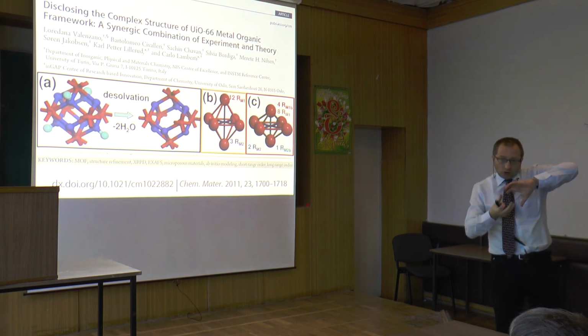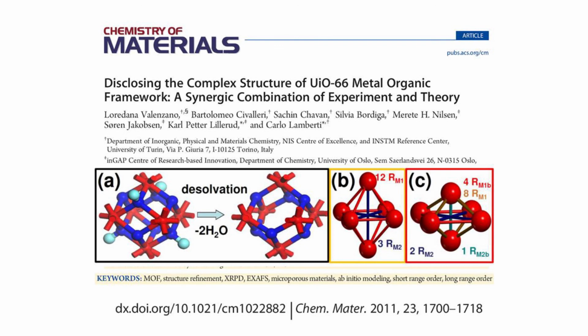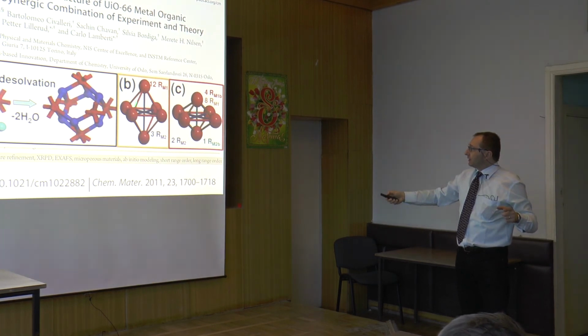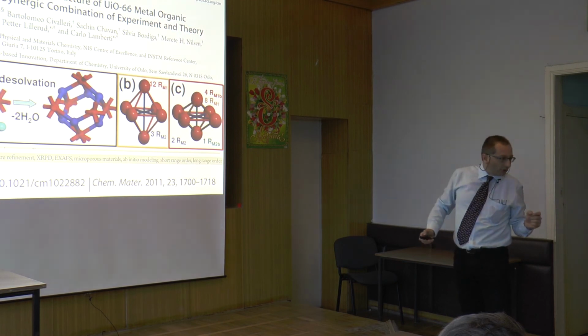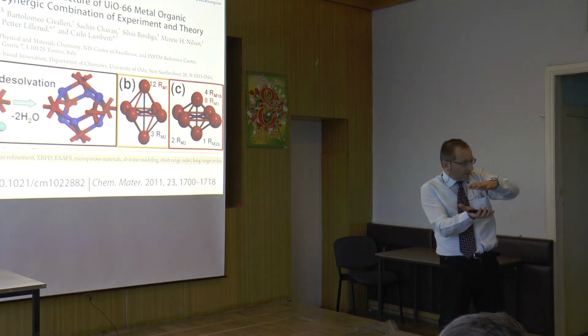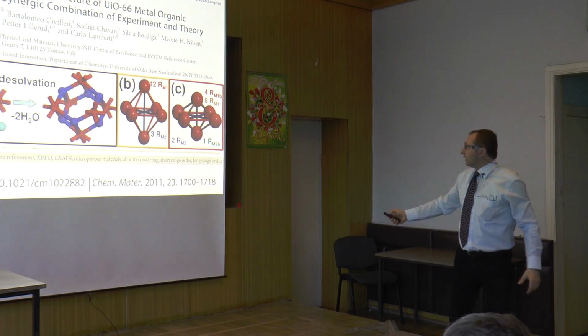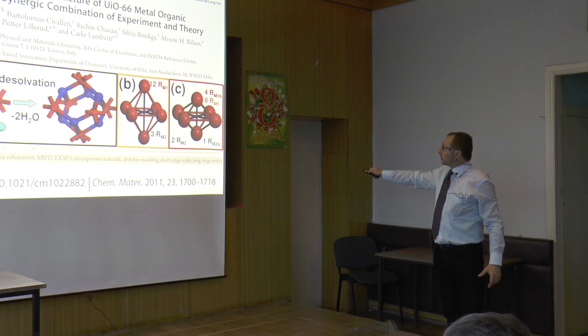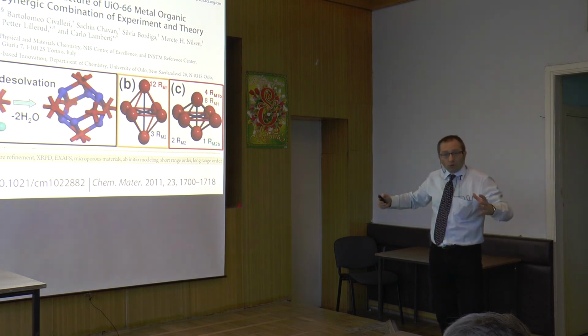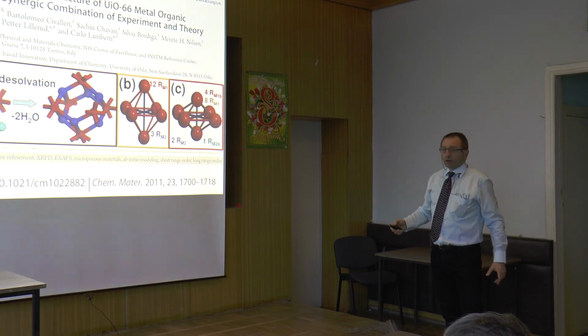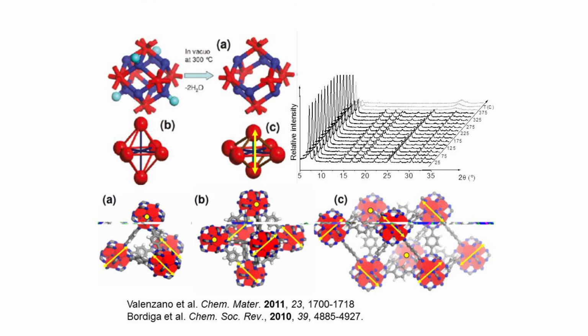This implies a distortion of the local geometry of the octahedron, where the local coordination in the first shell moves from 8 to 7. And it implies that you move from a perfect octahedron, where you have 12 equivalent zirconium distances and 3 equivalent diagonals, into a system like this, where you are squeezing your octahedron along one diagonal, and so you end up with 8 short zirconium distances and 4 long ones, and you have 2 long and 1 short diagonal. Okay, this is the idea of what I show you. This contraction is 0.2 Angstrom, which is amazing.